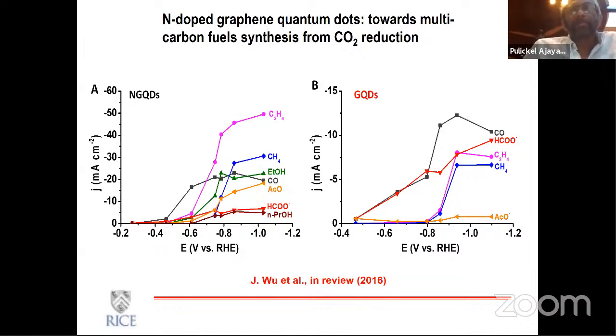So one of the things that we have done is these carbon-nitrogen quantum dots, which seem to be quite effective in CO2 reduction, which is again a hot field, but depends on what kind of dopants you can get into the carbon lattice and how large these quantum dots are. You get different performance.